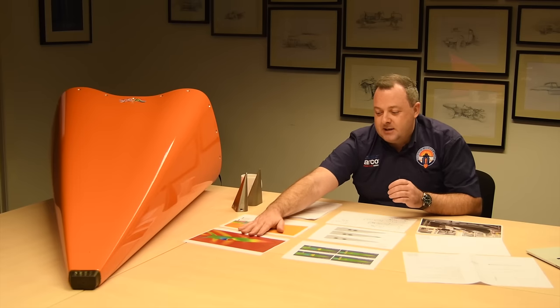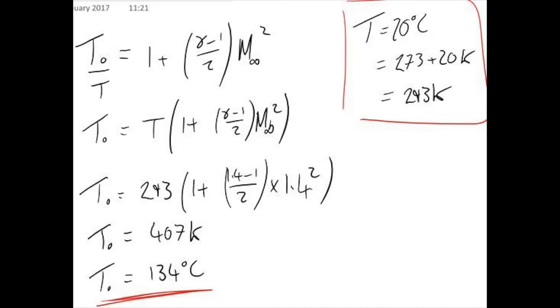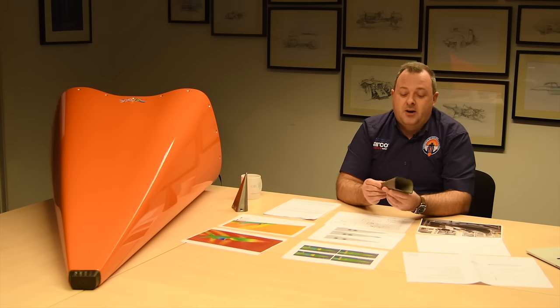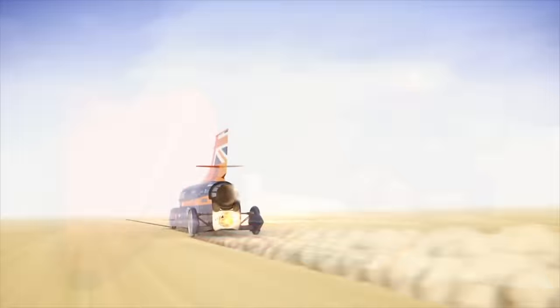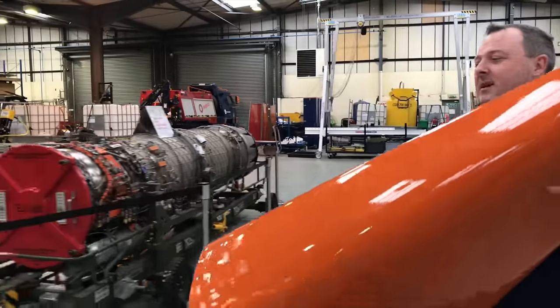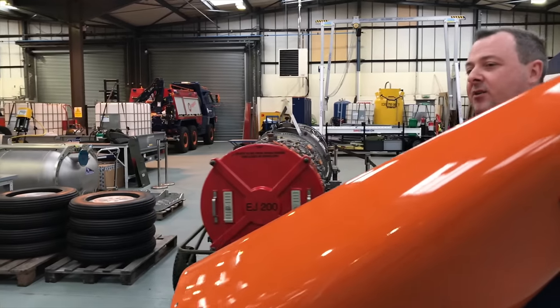It's still a pretty impressive shock wave. What does that shock wave do to that leading edge part? Well, it gets quite warm. From some scribblings from Dr. Ben, at 20 degrees desert temperature we're likely to see 134 degrees of heating for that component. That doesn't take into account conductive heat moving away into the rest of the structure or convective heat loss with airflow over the car at slower speeds. It's still getting hot, getting eroded by dust, and working really hard. Carbon fiber composites are normally really light structures, but in this case it's quite a heavy part — which makes sense when you think about how hard it's working.